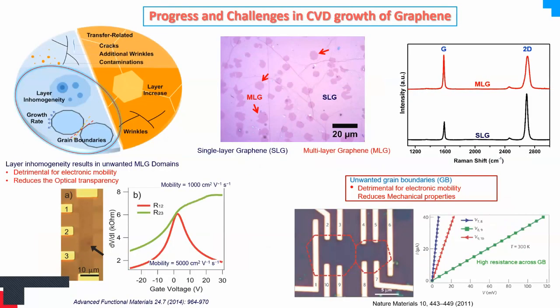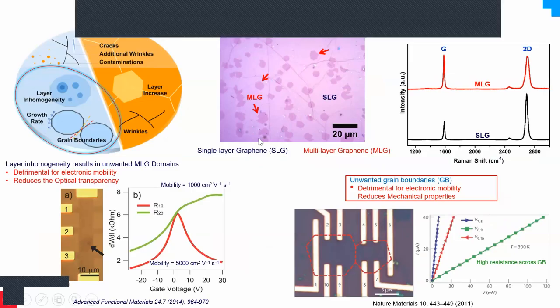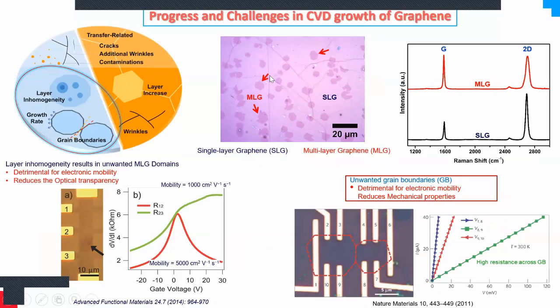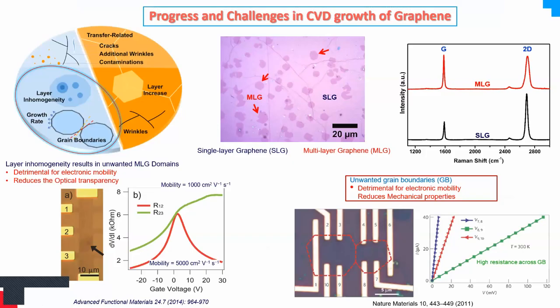So where I contributed to this field, there are a lot of challenges in the CVD growth of graphene. One of the challenges was basically, you see over here, this is the optical image of a monolayer, single layer graphene. But within the single layer, you can see there are small patches, which are basically multi-layer patches. But for the application, you want very uniform single layer graphene. You don't want small patches because this makes the film quality non-uniform, which can hurt your device performance.